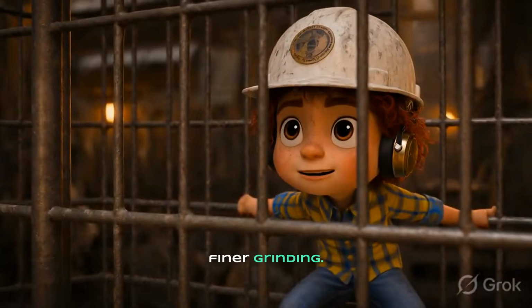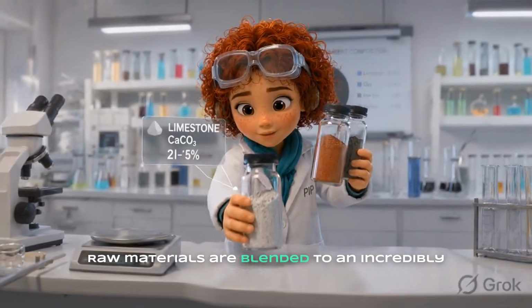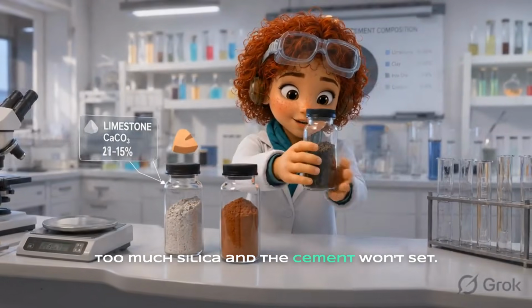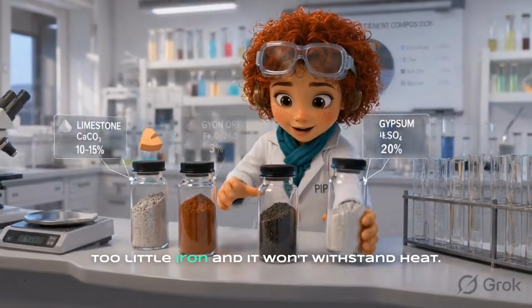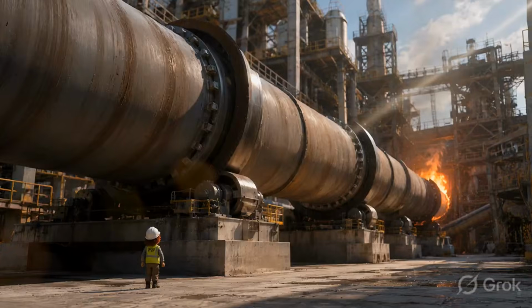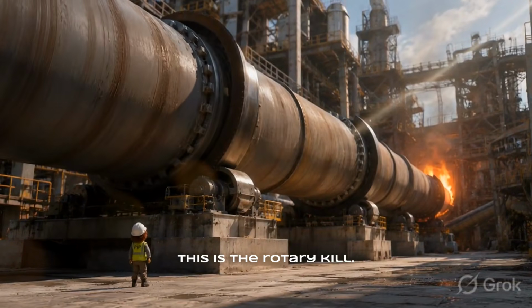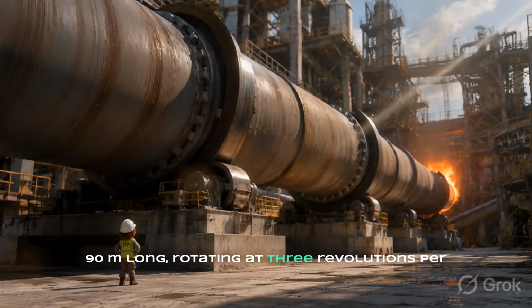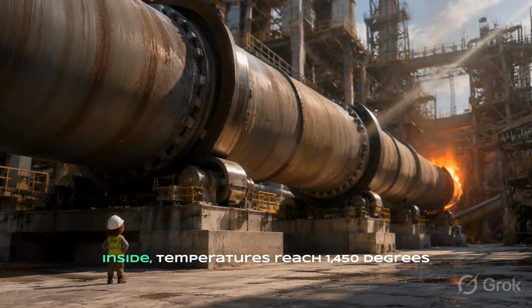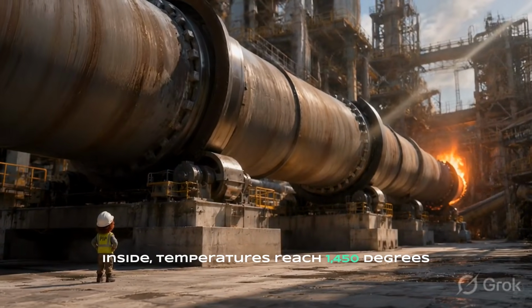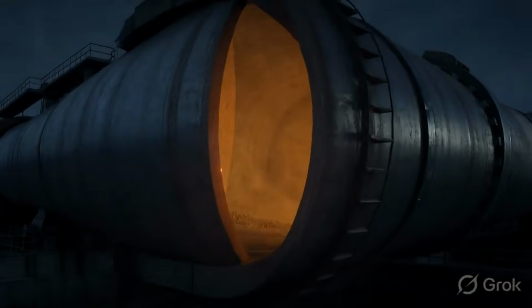ever finer grinding. Raw materials are blended to an incredibly precise formula. Too much silica and the cement won't set. Too little iron and it won't withstand heat. This is the rotary kiln, 90 meters long, rotating at 3 revolutions per minute. Inside, temperatures reach 1,450 degrees Celsius.